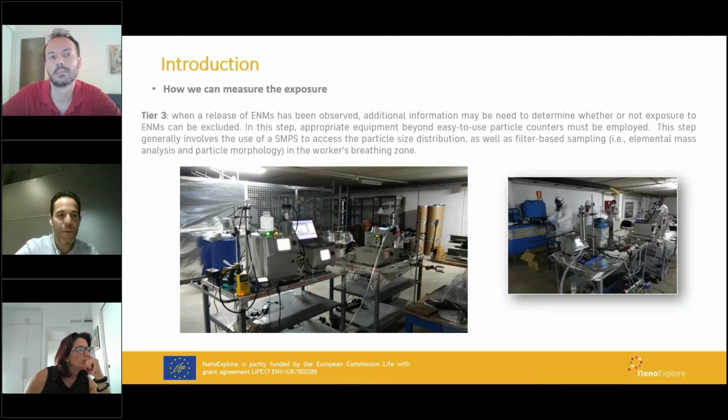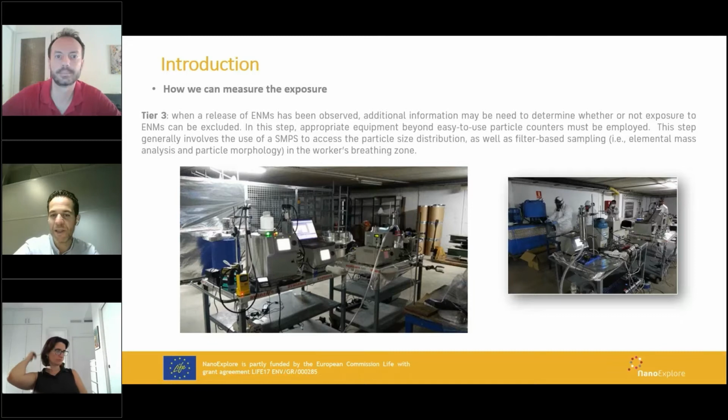For example, the SMPS, that tells you about the particle size distribution of the materials, the aerodynamic particle sizer, for example, also to measure inhalable and respirable particles in the area. We can also use impactors to collect on filters materials under different size ranges, and then go to the microscopy and determine the chemistry of the materials.